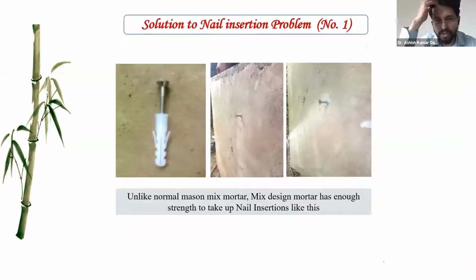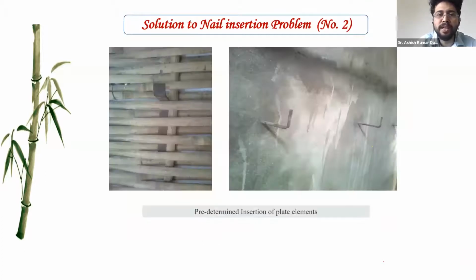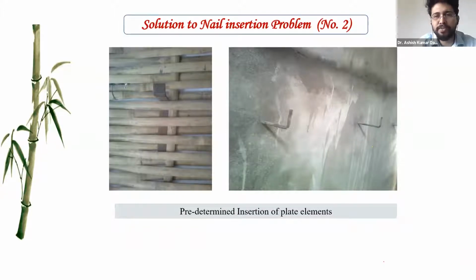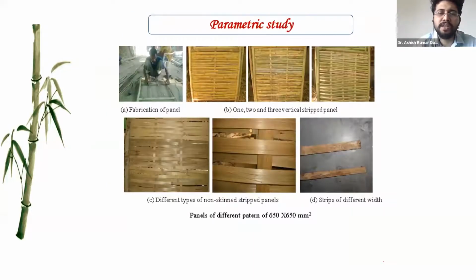And also nail insertion, which is a problem in the case of normal mortar mix. But in the case of the mix design, the mortar has enough strength to carry the nail insertion, and we studied everything. Then predetermined insertion of the plate in the flat channel we also studied for anchorage purposes. Then different parametric studies in the fabrication process with the number of vertical supporting strips, with non-skin and skinned strips weaving. Then the effect of the width of the strips on the panel strength.